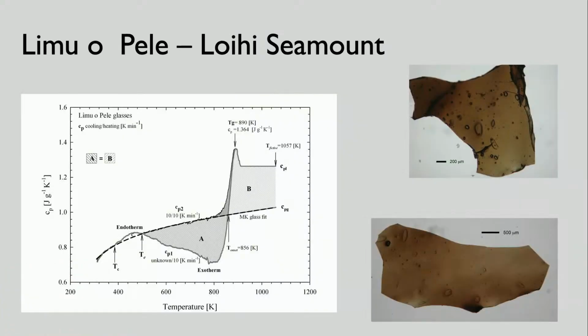This is the fastest cooled glass we've ever seen. This is what its curve of CP with temperature looks like. So almost no overshoot, but a huge undershoot when you go into the glass transition. And this undershoot is always a reflection of really fast quenching. This is from a submarine seamount in the Hawaiian chain, where the seawater quenched it very quickly at high pressure, and where its morphology is shards of glass which were between bubbles. So it was already extremely exposed morphologically to the cooling agent, which was high pressure seawater. And you have super fast quenching of these glasses.